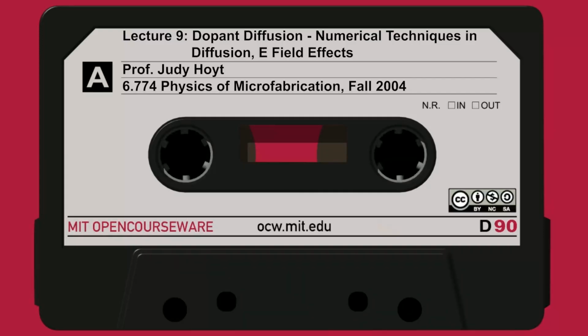So the final boron profile now, shown by the blue dashed line, has this little hump in it and then a dip, and that little dip occurs right near where the junction is, right near where the arsenic and the boron cross. And there's no way by Fickian diffusion you would ever predict that a constant profile of boron would end up looking the way it does in this particular plot. Again, that's because of the second term, the electric field term, that non-Fickian term.